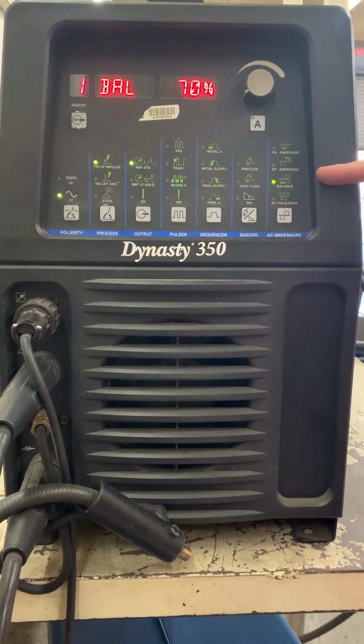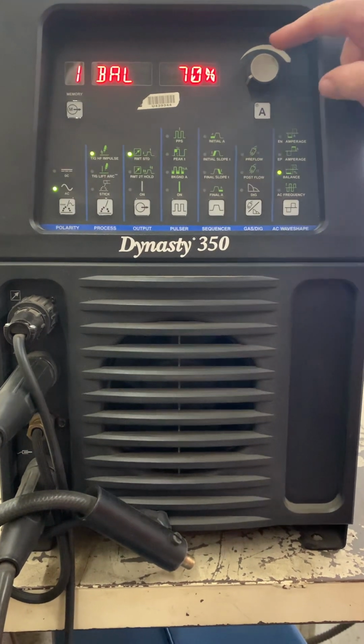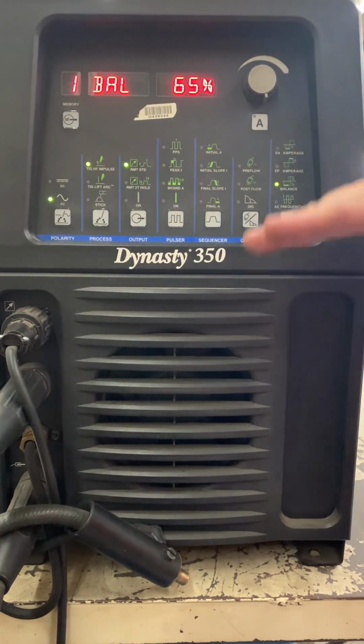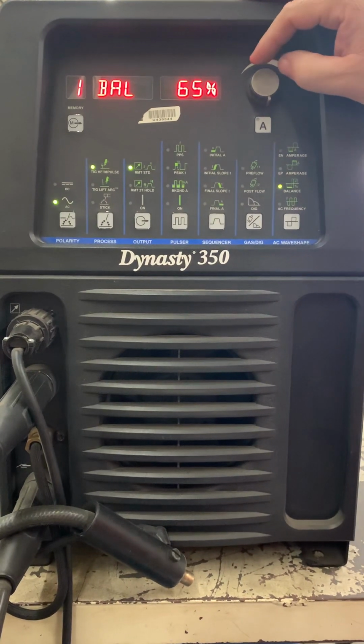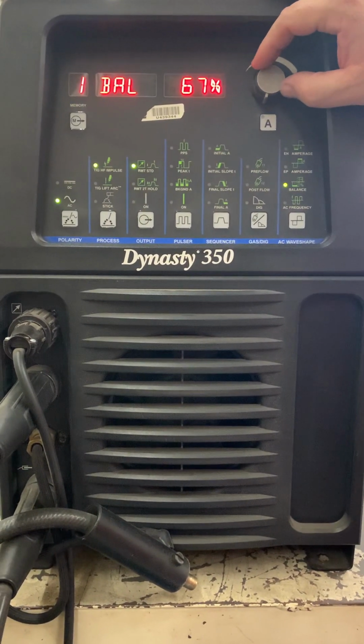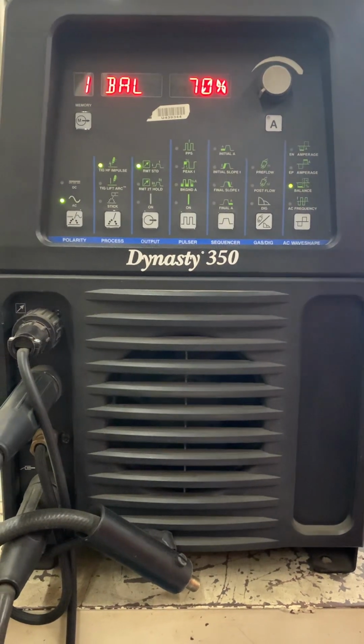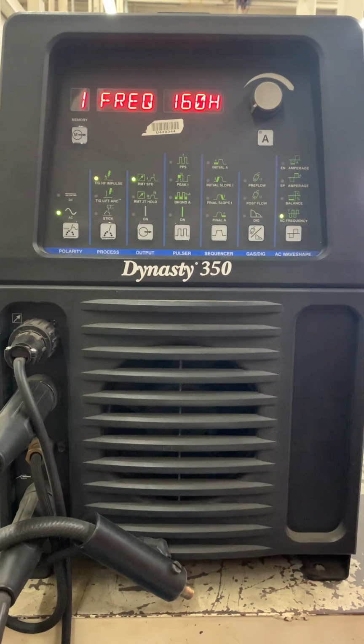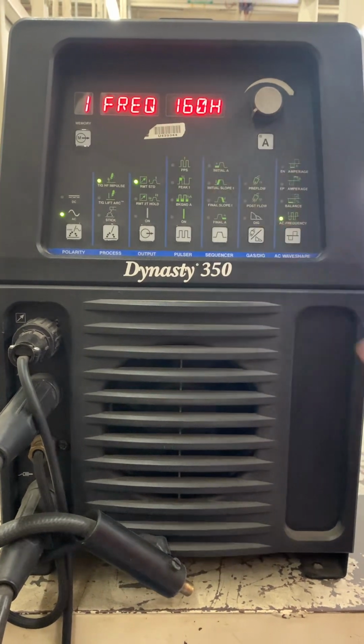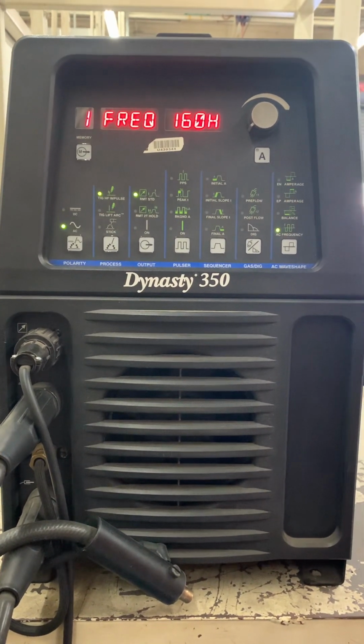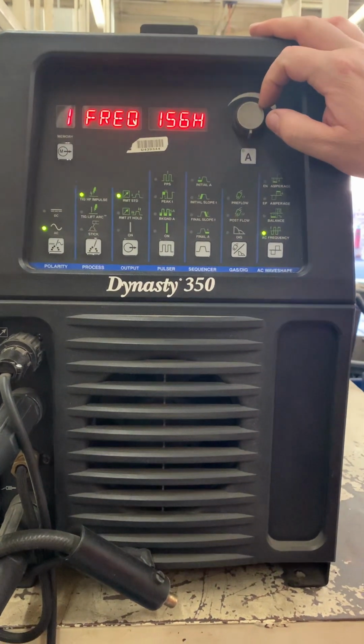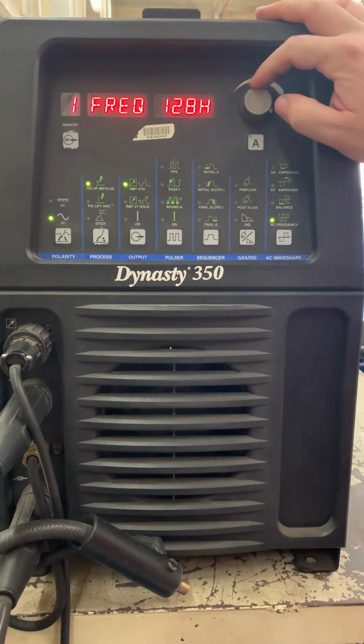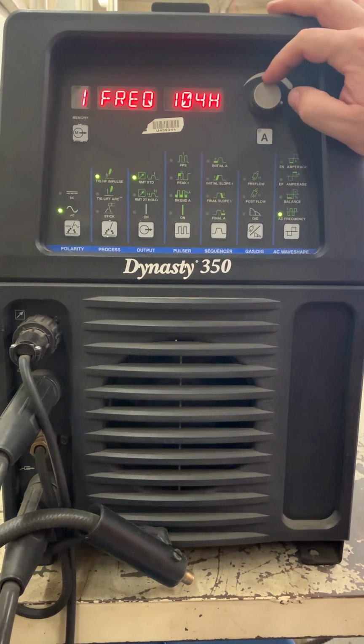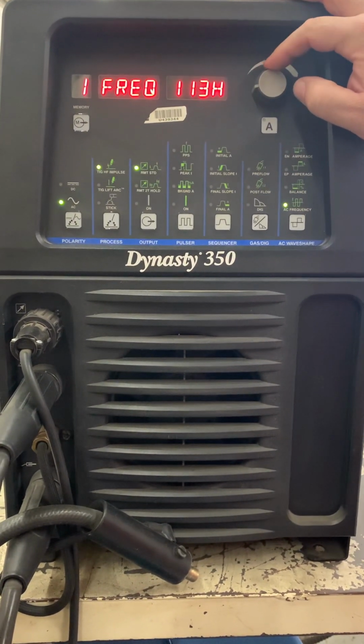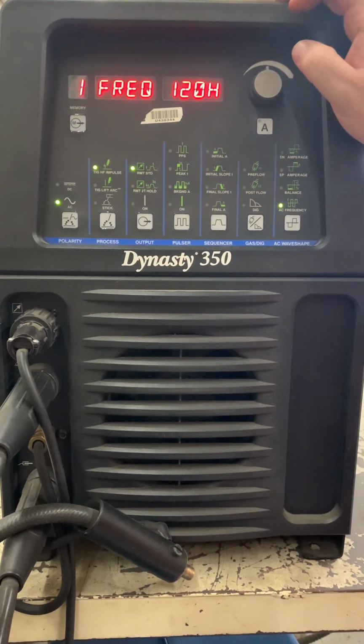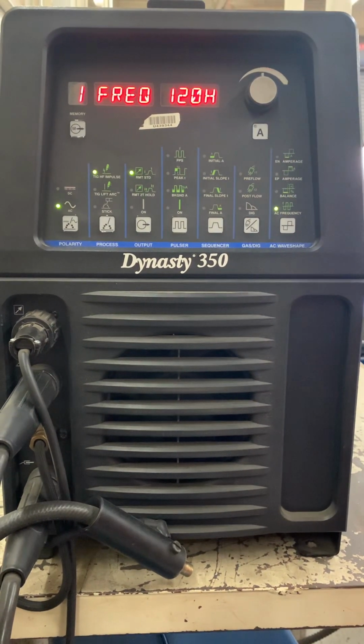If you have to go much below around 62 to 65%, meaning you're increasing your cleaning action, we probably need to make sure the oxides on the aluminum plate have been removed more thoroughly. So we're gonna set this at 70. And last but not least, our AC frequency. Like mentioned before, non-advanced square wave machines typically are stuck at 60 Hertz. For AC aluminum, we want to be running typically between 100 Hertz and 120 to 150 depending on your style of welding. I like 120 personally.